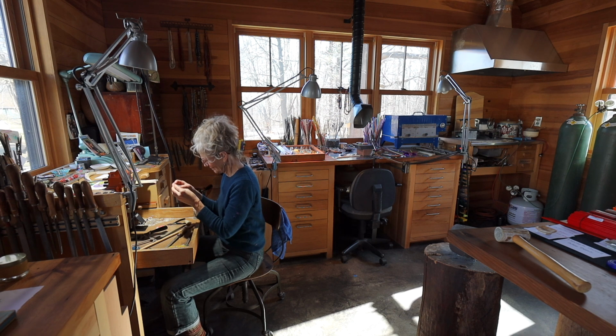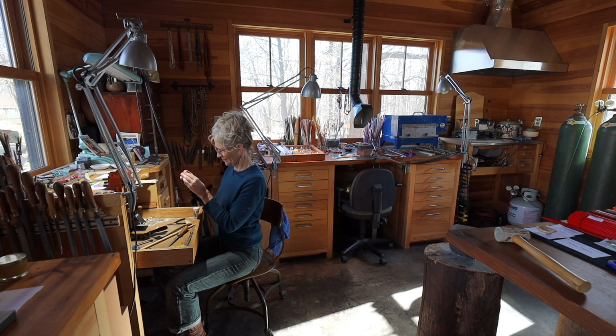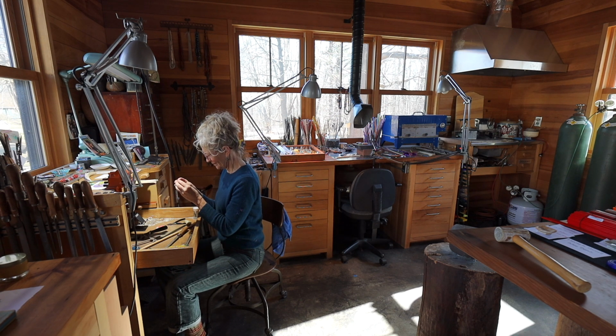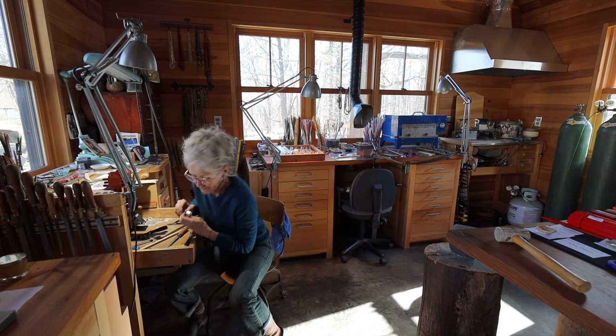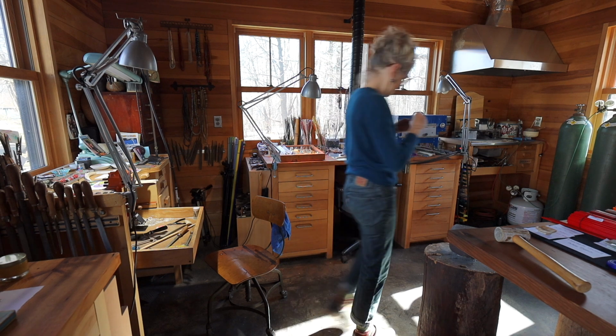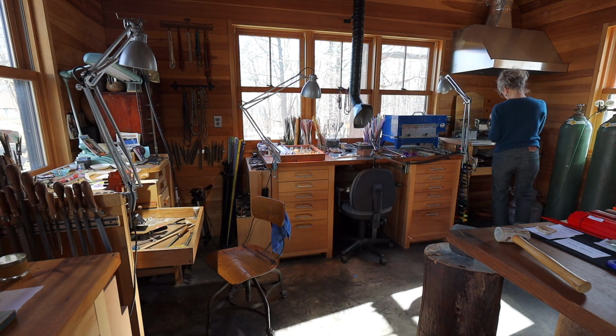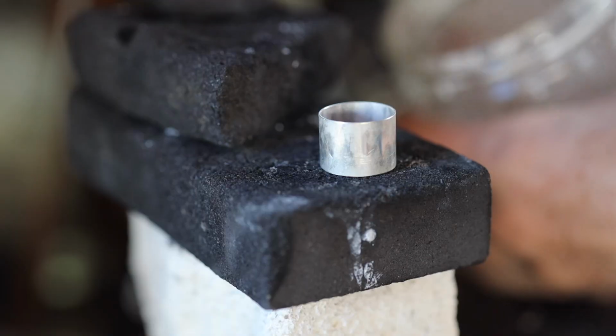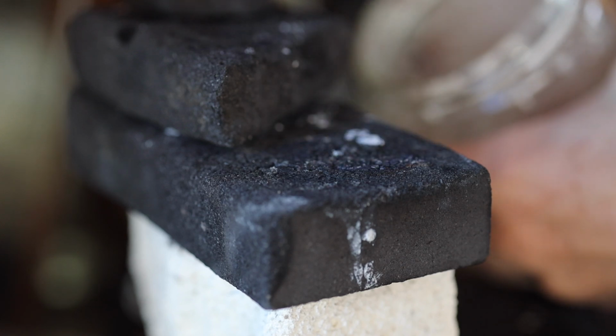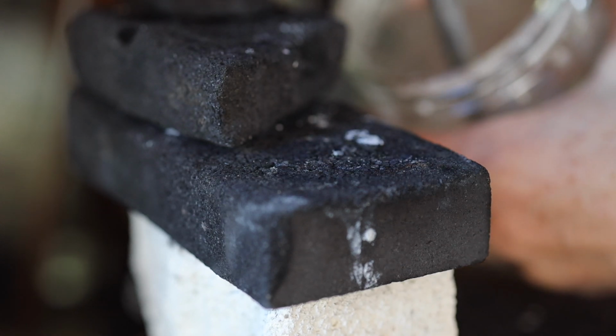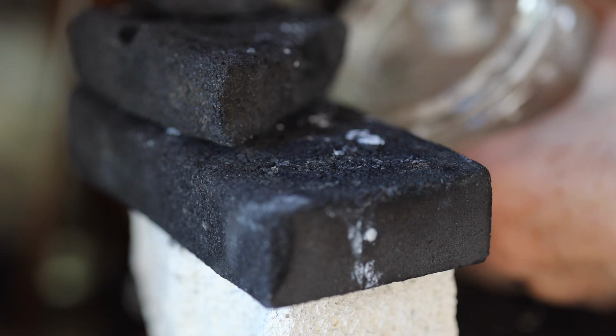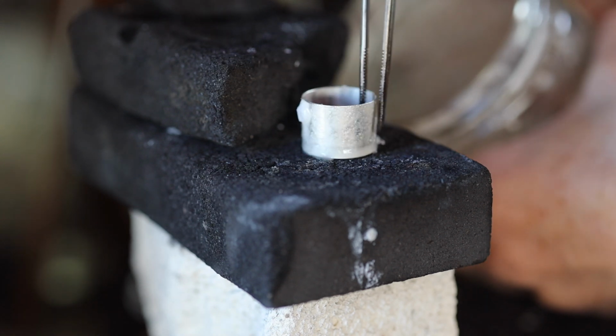The risk of a really big fold over is that you're asking the silver to move that much more, and it can result in a crack or a tear in the silver. But I've been able to work a pretty good stretch out of the silver over the years by really working carefully and slowly. So I'll show you how it works here.